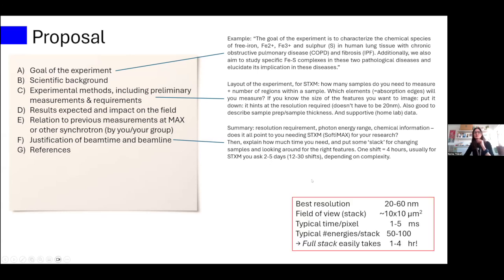So how do you then calculate that? Well, the best resolution will set your step size, right? We do the images pixel by pixel. The field of view: if you want to look at some smaller area inside a cell, for instance, or inside a larger structure, you may want to have a bit of an overview of the larger structure. So at maximum, something that is workable is 10 by 10 micron, but it can be smaller, like 5 by 5 or 2 by 6 or whatever. The typical time that you would spend per pixel is 1 to 5 milliseconds, depending a little bit on which edge you are imaging and the abundance of that element in your sample. If it's a very rare element in your sample, of course, you'd have to measure a bit longer.